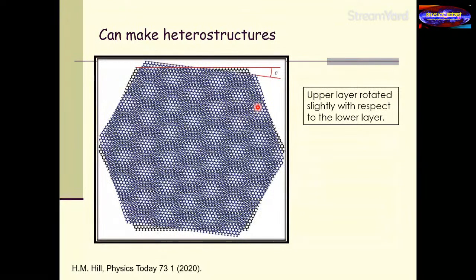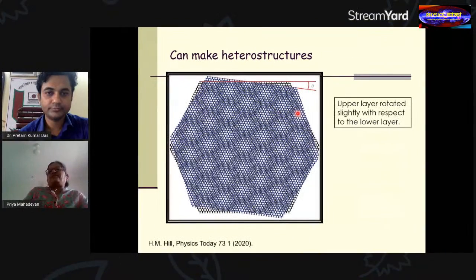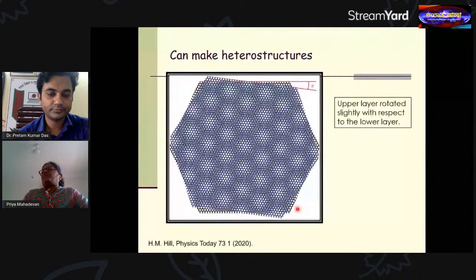The other aspect which you can immediately see, which I pointed out, is that in the previous case, I just needed that small box, which I described as the unit cell. I took the two atoms which were in that box, and the vectors associated with the box, and then I could generate the whole lattice for you. However, in this case, what you can see is that I cannot, since this one is rotated with respect to the lower layer, I would be talking about much larger unit cells.